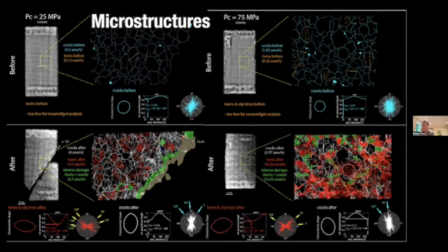Now, if we look at the experiment that was conducted at 75 MPa confining pressure, where no macroscopic fault developed, we can see again that there's quite a bit of cracks, and they are oriented in a similar orientation. So those are probably mostly mode 1 cracks, but there is a much higher density of the crystal plastic defects, which are shown in red, and again, the orientation of these crystal plastic defects is consistent with the planes where the maximum shear stress is resolved.